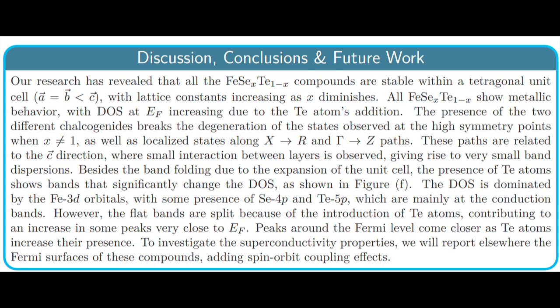The density of states is dominated by the iron 3d orbitals with some presence of selenium 4p and tellurium 5p, which are mainly in the conduction bands. However, the flat bands are split because of the introduction of tellurium atoms, contributing to an increase in some peaks very close to the Fermi level. Peaks around the Fermi level come closer as tellurium atoms increase their presence. To investigate the superconductivity properties, we will report elsewhere the Fermi surface of these compounds, adding spin orbit coupling effects.